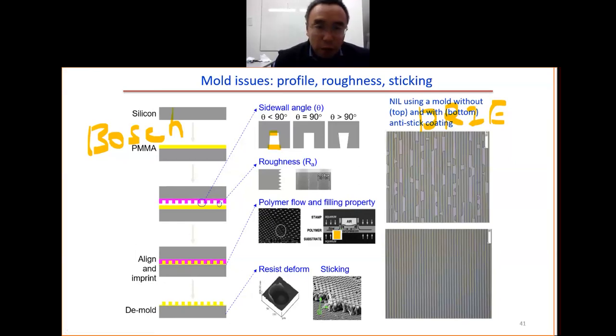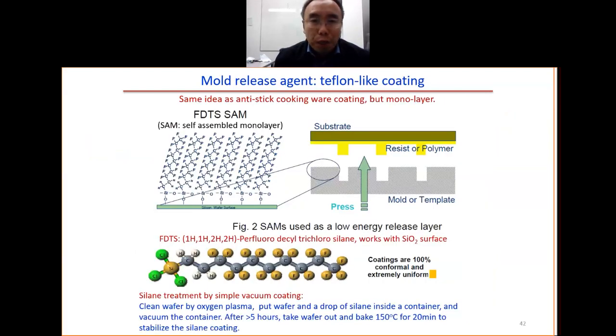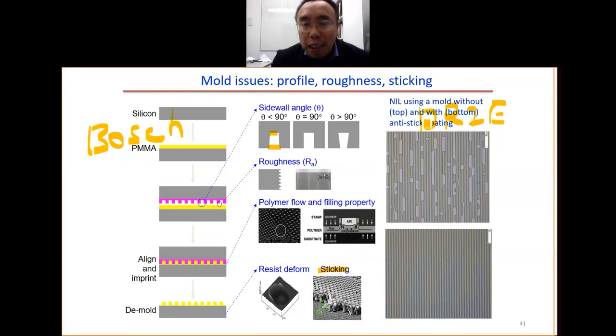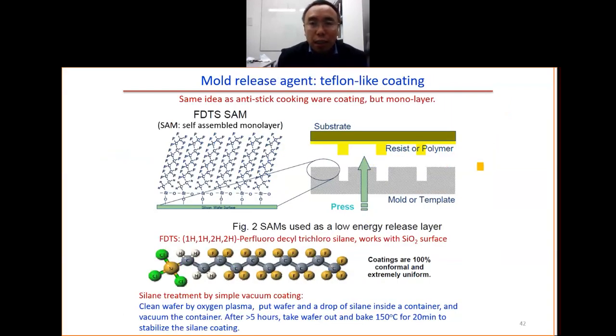Finally is the resist deformation. You can see here the resist got deformed, and the sticking problem. This is also a major problem. As you can see here, on the top side, the mold without anti-sticking, anti-adhesion coating, you get the peel off. The resist here got peeled off. On the bottom side, with the anti-sticking coating, there is no peeling off. So how to do this anti-sticking coating? Actually, this is the major secret for imprint lithography.